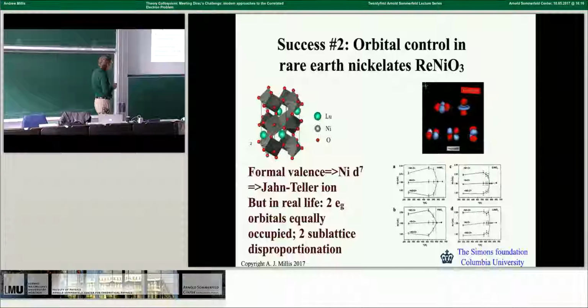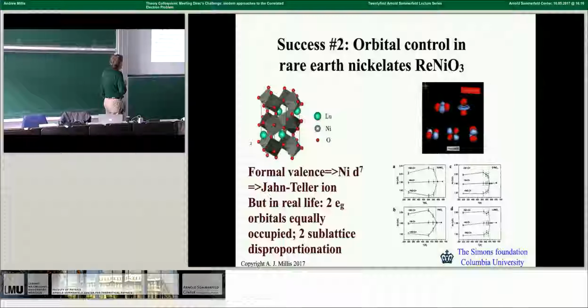All right, but let me go back to these rare earth nickelate materials. I had mentioned to you lanthanum nickel oxide, LaNiO3. This is a moderately correlated metal. Every other material you make by putting something chemically similar to lanthanum here, yttrium, europium, neodymium, lutetium, is actually an insulator. It has a high temperature phase transition in which the bonds disproportionate. That's shown here.